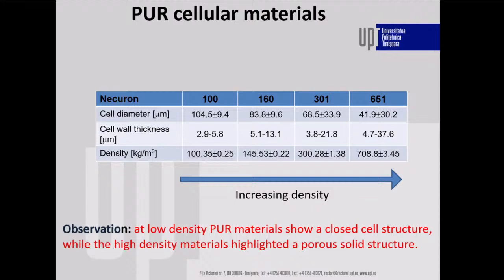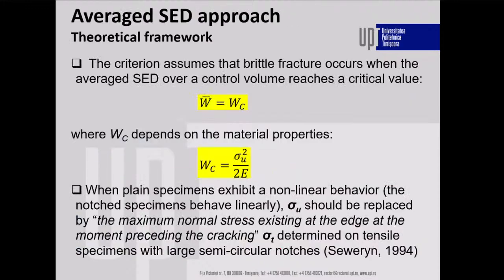The cell wall thickness is increasing. So what we can see here is that at low density, the polyurethane materials show a closed cell structure, while at high density, they show a porous solid structure. Our previous works show that we can apply the theory of critical distance, and the critical length was related to the cell size.